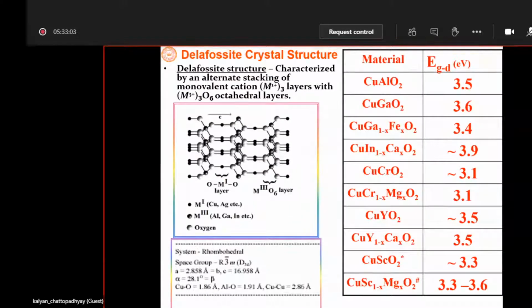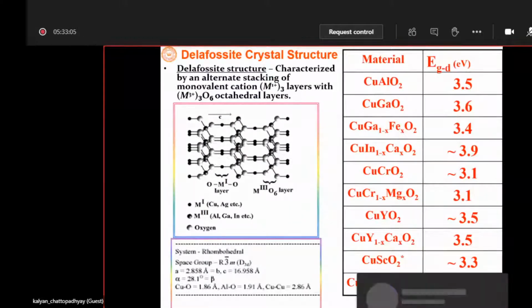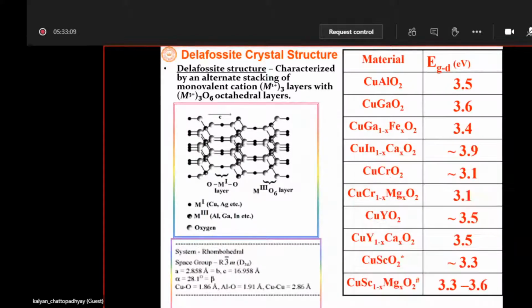And based on this criteria, a large number of systems have been studied. The prototype is copper aluminum oxide, which has a band gap of 3.5 electron volt, and then copper gallium oxide. These are basically delafossite structures with general structure ABO2. You have the doping possibilities both at the A site and B site, and a large number of compounds can be synthesized. The major criterion is that the band gap should be greater than 3.1 electron volt, so that it remains transparent in the visible region.